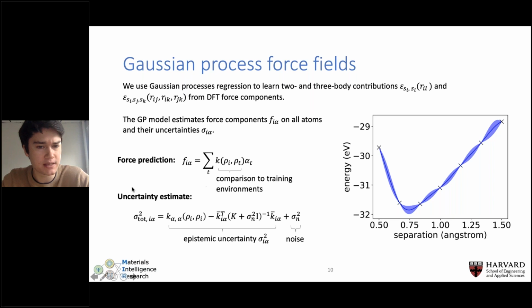And the really convenient thing about GPs that sets it apart from other regression models like neural networks is that you can get an explicit analytic expression for the variance of the predictive posterior. So I've written out the formula here. The key thing I want to draw your attention to is that the variance breaks down into two different contributions. There's one contribution that I'll call the epistemic uncertainty. This is characterizing essentially how far away you are from the training data. And then there's this noise parameter that gets optimized by maximizing the log marginal likelihood. And it tells you how well your model is doing overall, what is the baseline error level of the model. And these two pieces of the uncertainty can give you really rich information about how the model is doing at a particular test point.